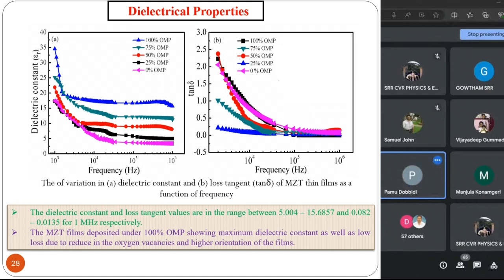Next slide, please. Yeah, so you look at now, when we did the dielectric properties at lower frequencies in the case of bulk material, and now the dielectric properties with the thin films at the lower frequency, both the properties are similar. In that case, when we made a disc, we needed 1 gram of powder to make a disc of 10 mm diameter and 1 mm thickness. But in the case of thin film, it is 200 nanometers, which is very little. You can look at the difference between 1 mm thickness and 200 nanometers. And interestingly, both the materials show the same response.